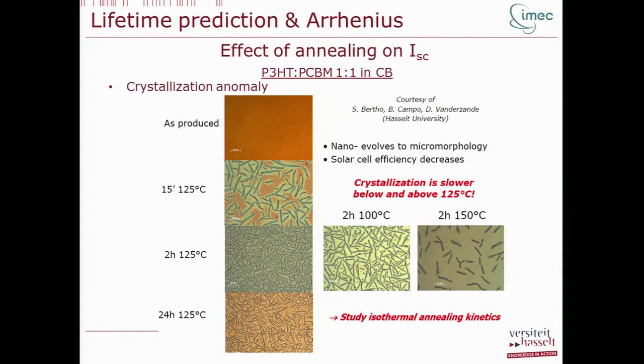So what we see here are images of P3HT:PCBM that have been annealed in the dark at various temperatures. Here you see 2 hours at 100 degrees Celsius, 2 hours at 125, and here at 150. And what we see is that the crystallization is slower below and above 125 degrees Celsius. So although we are at a higher temperature, this phase separation is not going faster. So it's a crystallization anomaly, which is counterintuitive.